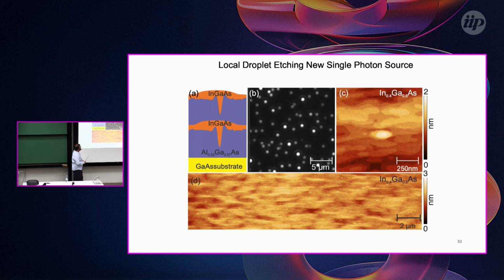And here is just the image of the setup that we used to see the density. And this is an atomic force microscope image showing how the nano hole looks after the filling. Basically, what I was measuring was here in the sample. And this is a big scan that I did. Each of these small spots is a nano hole after filling, but you don't have the Stranski-Krastanov growth formation.